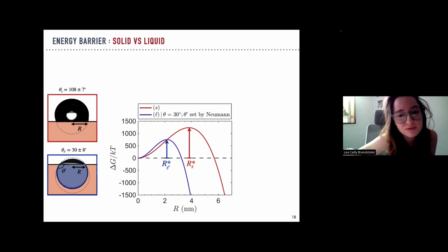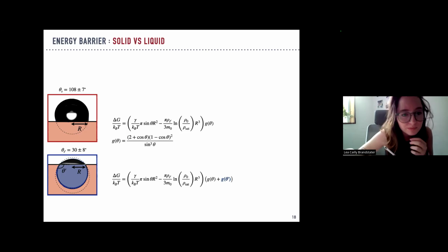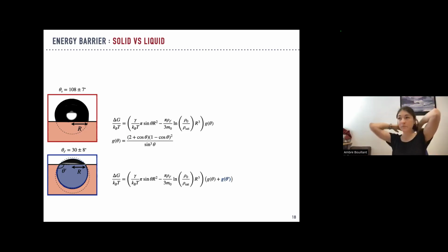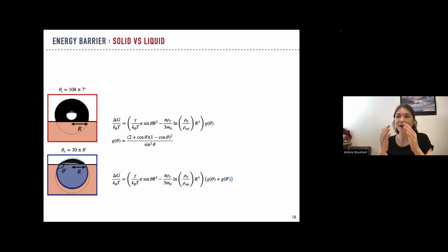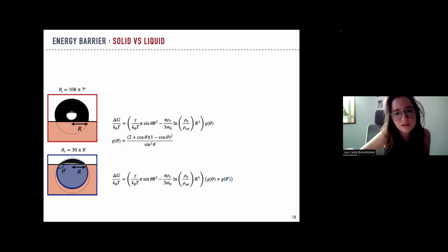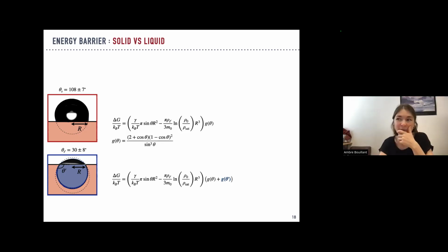You cannot have any velocity pressure whenever it comes to... yeah. So this is really a thermodynamical picture. Actually, it's just to look at the energetics of this system, to see whether you will have thermodynamics that will drive the nucleation and growth. Mostly. But then for the dynamics, I completely agree that the drop will grow, and then it will have to carry its ridge and its deformation in the gel. So for the dynamics, it's something more subtle, but here it's just to compute the threshold radius upon which we should see droplets nucleating.